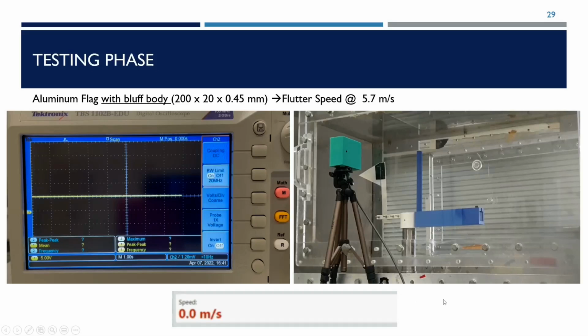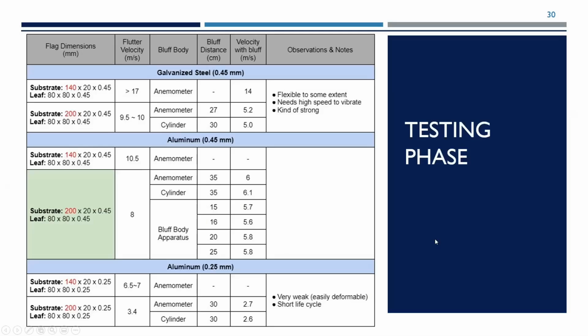In this test, we used our flag of choice, and we attached a bluff body to it. From this test, we can conclude that the flutter velocity of the flag with the bluff body is around 5.7 meters per second. This table summarizes all the results of using different flag dimensions, different flag material, different bluff body sizes, and different bluff body distances.